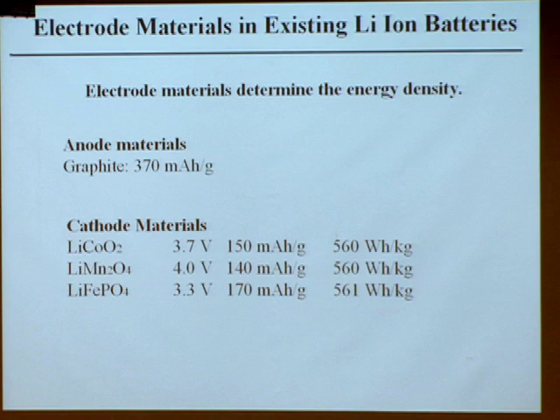Looking at all these battery materials working so far, anode, that's negative electrode, is dominated by carbon. It can store the number of charge, that's 370 milliamp hour per gram. So just forget about the unit. This is conventional unit. Just remember this number a little bit. And the cathode materials is more or less a lithium cobalt oxide or lithium manganese oxide spinel or lithium iron phosphate. Among this big family of the materials, they more or less have the similar energy density as well, a similar charge storage capacity. That is also why, with only these four materials, they really dominate the market.